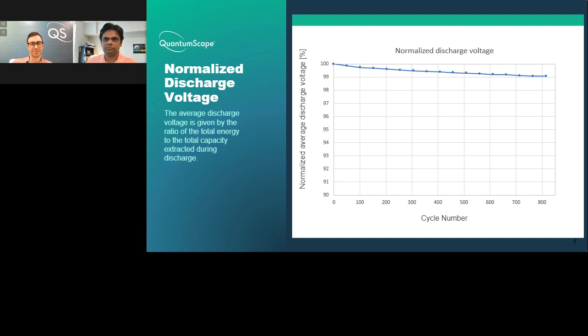And so what you can see is there's very modest change in the discharge voltage. There's about 1% change in the discharge voltage over these 800 cycles. So it's showing again, like Venkat was saying, stable performance of the battery one cycle to the next, predictable performance.